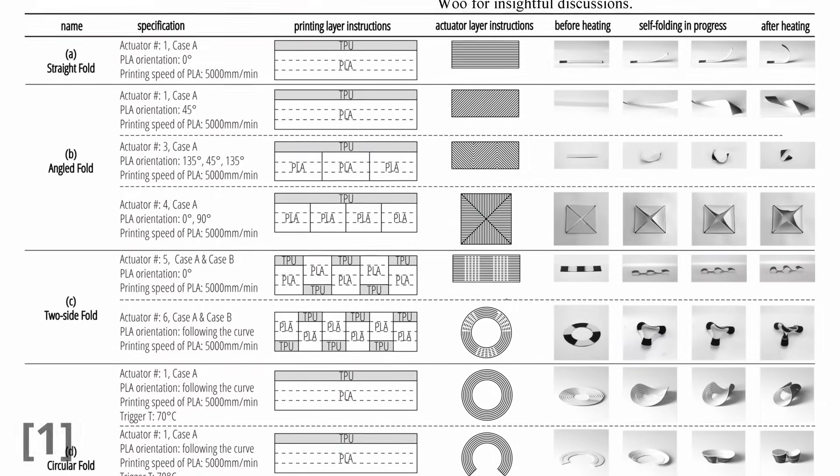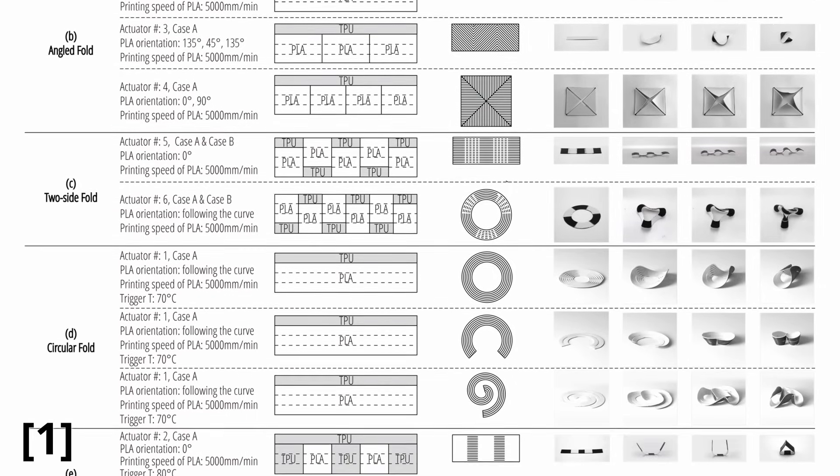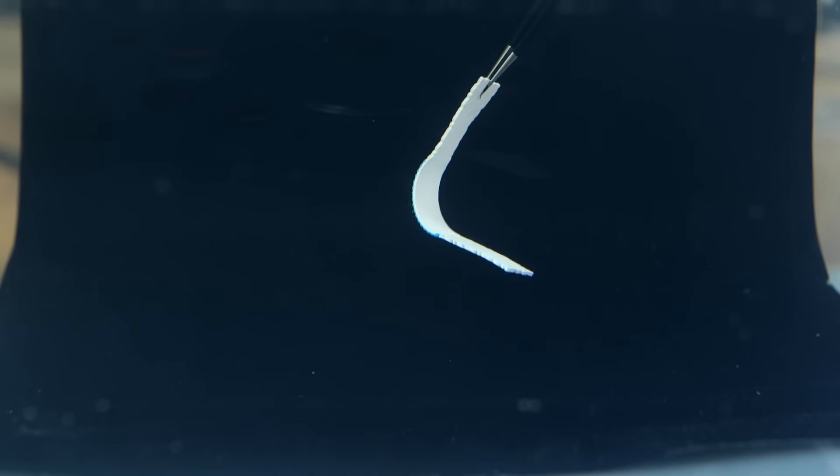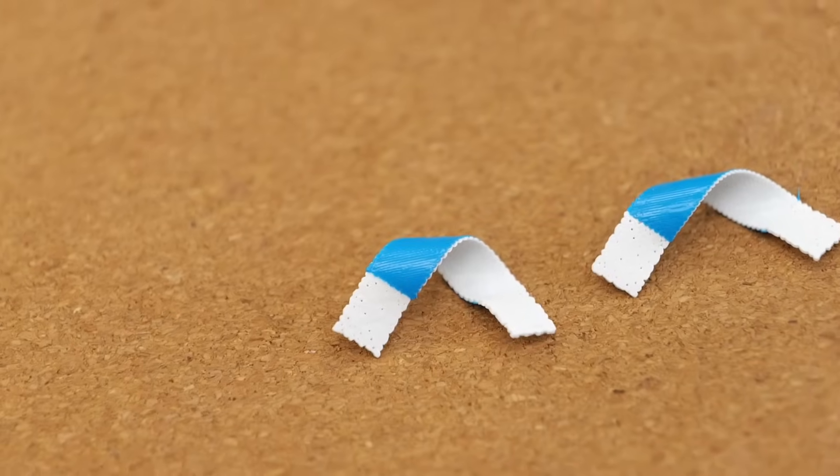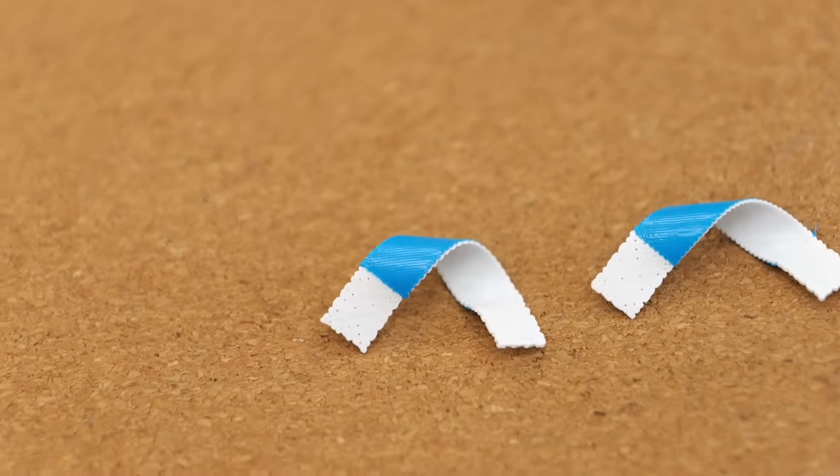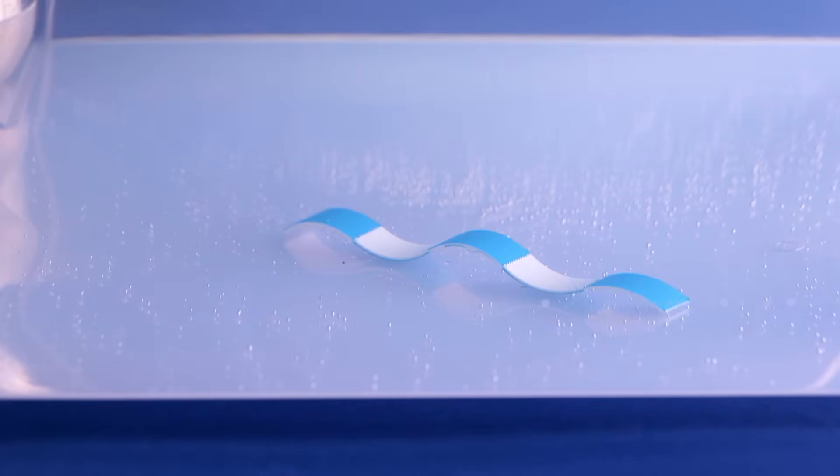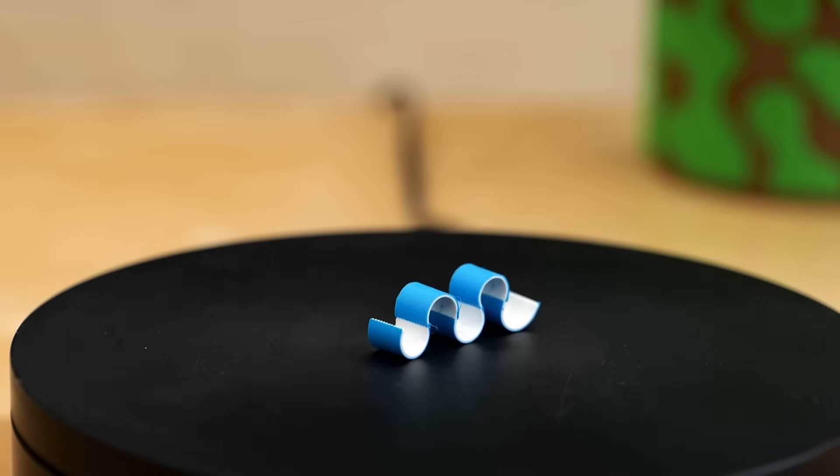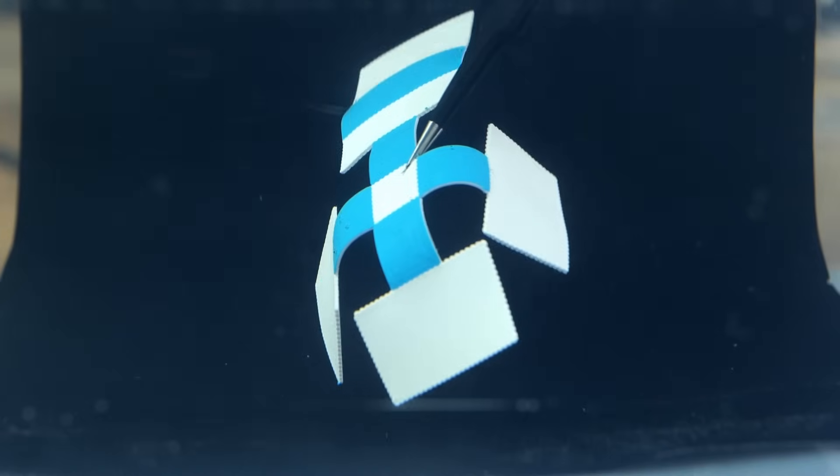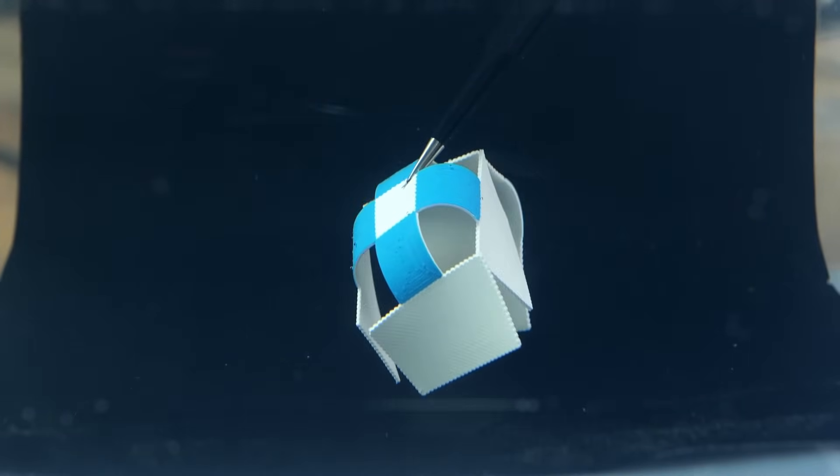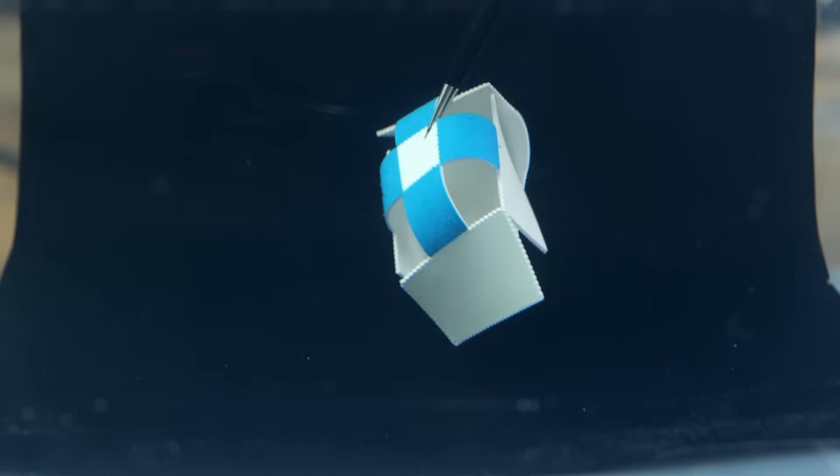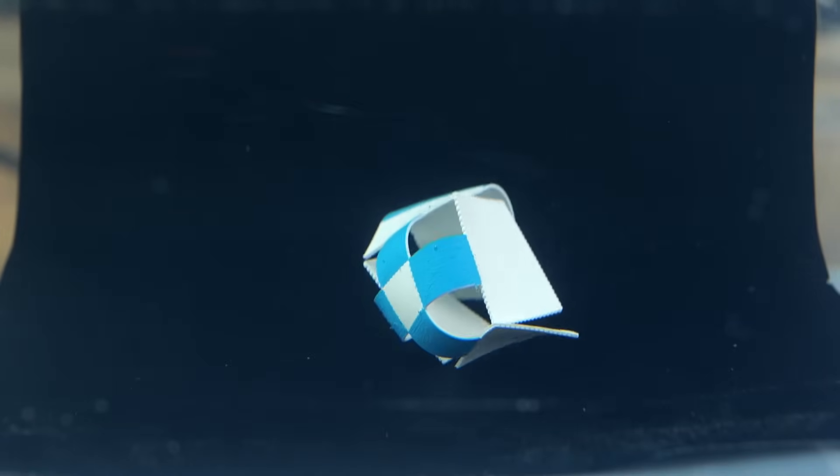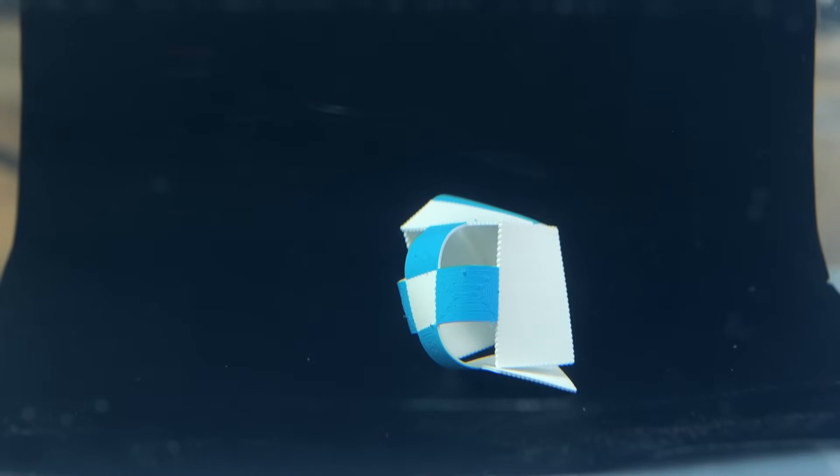By combining printing direction and layer stackup, we can customize how the part will deform. If our printing direction is along the strip, it simply folds up. If we print at a 45-degree angle, the part will twist. If we alternate the stackup and create sections where the active layer is on the top and others where it is on the bottom, we can design a part that resembles a snake. Of course, we can make it even more complex. In this way, by adjusting the layer stackup and printing orientation, we can basically program the final morphed shape into our flat 3D printed part. And that's the reason why we can call this method even 4D printing.